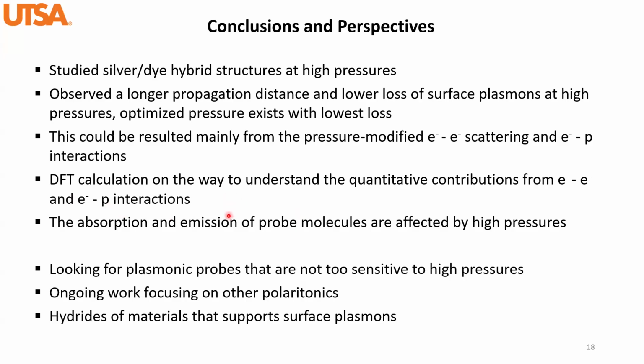Please be patient. And also we have tried to analyze how our probe dye molecules were affected by the high pressure. It seems that yes and no. It has no effect on how we interpret our plasmon propagation data, because we're just relying on the emission intensity from rhodamine 6G, not at selected wavelengths. But it causes some problems, because the reduced absorbance of the dye at high pressure makes the surface plasmon polariton really hard to show up, even when it is there. And also, the reduced emission requires us to keep adjusting the laser intensity, which is also a problem.